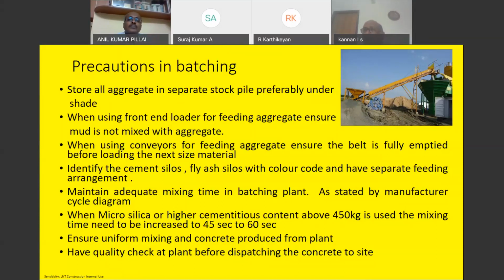So the general tendency of people is, no sir, I'm going to transport it for 45 minutes, sir, my concrete will get mixed in the transit truck. Nothing will happen, because your truck during transit is going to operate only at 2 to 3 revolutions per minute. And even though it doesn't have any mixing arms inside, your concrete is not going to mix.